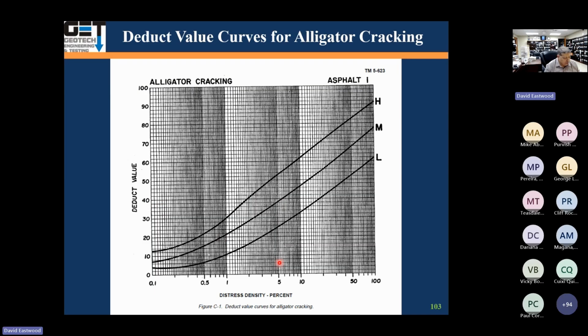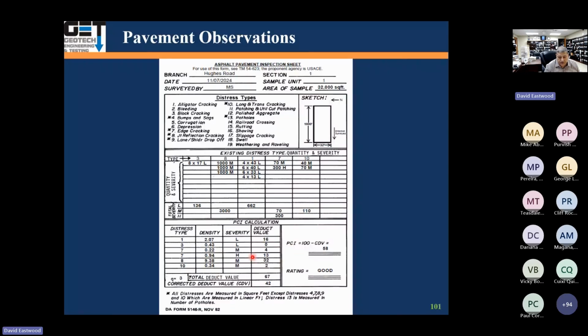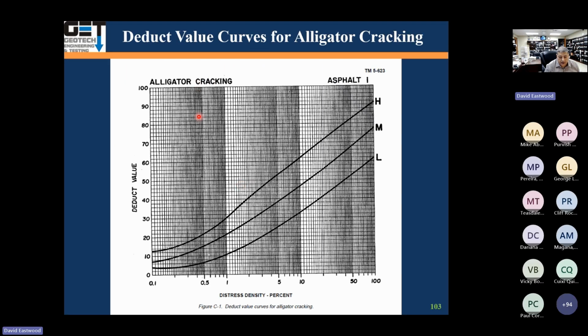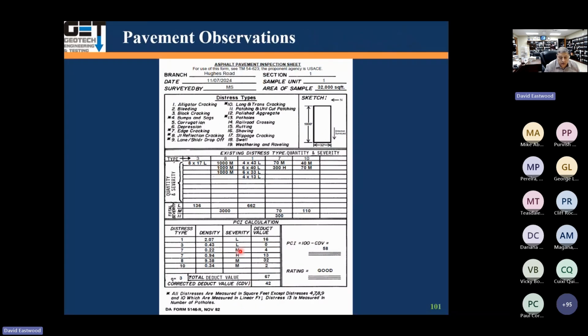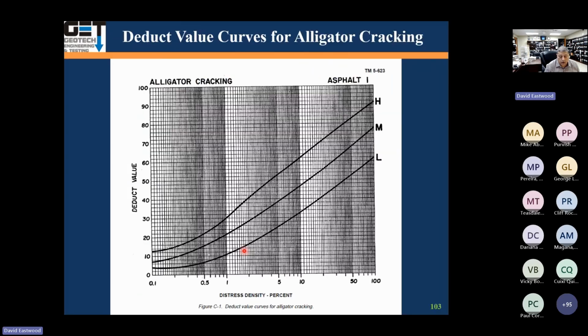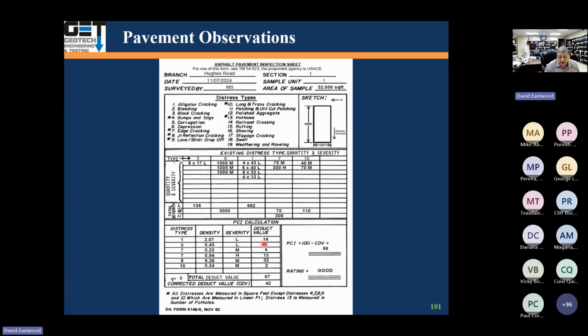Okay, so going back here, if you got 2.07 density here for type 1, which is alligator cracking, you go to alligator cracking at 2. So that's medium. That was low, I think. Let me go back again. I forgot what it was. Okay, it was low. So 2 low, you get a deduct value of roughly about 15 or so. So it's 16, okay? So you get a deduct value of 16.